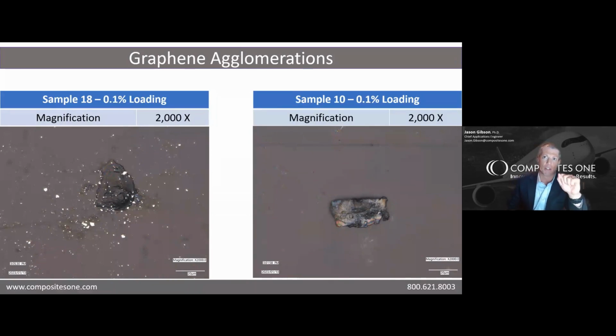The sample on the left there is from our sample 18 at 0.1% loading, and the sample on the right is from our sample 10 at 0.1% loading. Both of these samples performed well in our testing, but sample 18 on the left performed better than sample 10 on the right. Now you can see that visually these agglomerations look different. This speaks to the possibilities of the difference in the type of graphene, the functionalization, the morphology, and other physical characteristics. However, this does not lead us to any definitive conclusion other than the simple fact that these samples were all different.